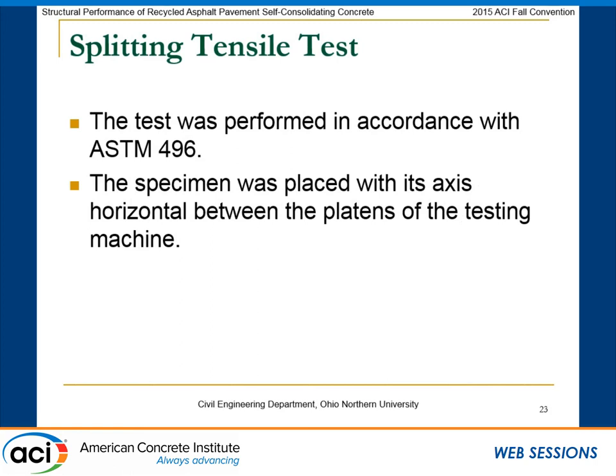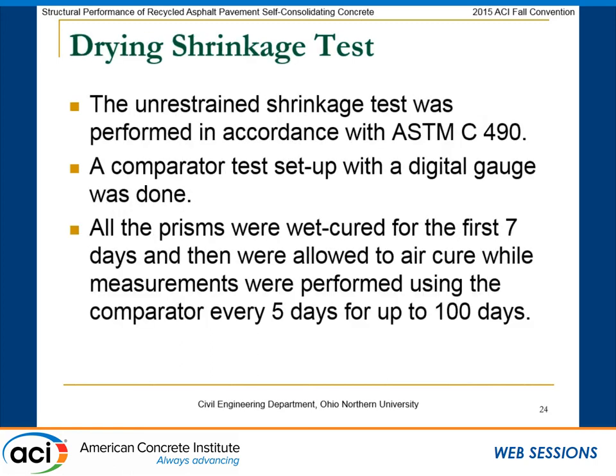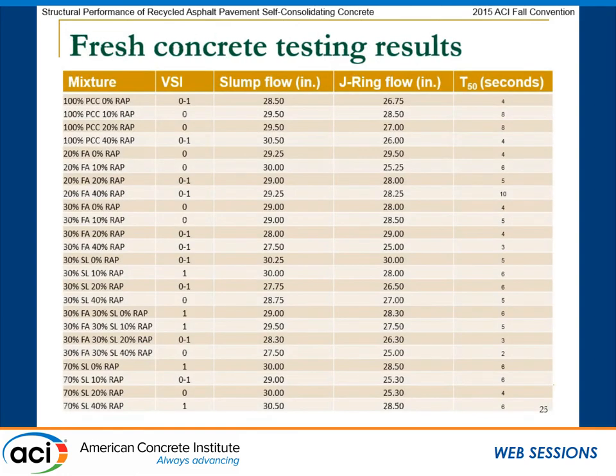This is the ASTM C496. For drying shrinkage, we did unrestrained shrinkage, ASTM C490. The digital gauge was used to measure the change in the length of the concrete prisms. The concrete prisms were wet cured for 7 days and then were taken out and put on a table to air cure for the rest of the time. We took measurements every 5 days for a period of 100 days.